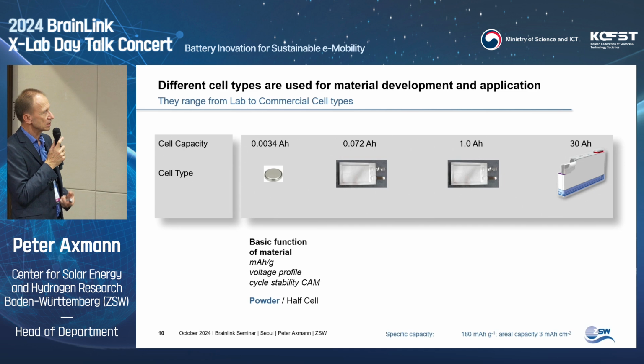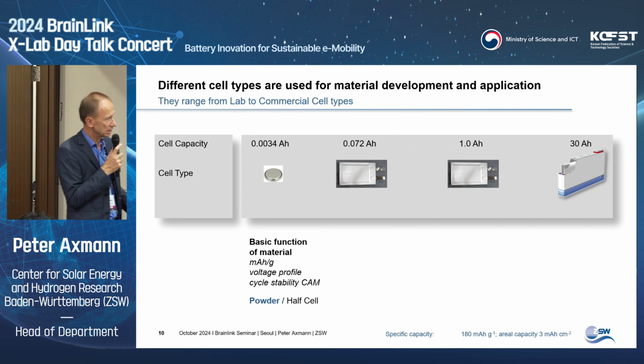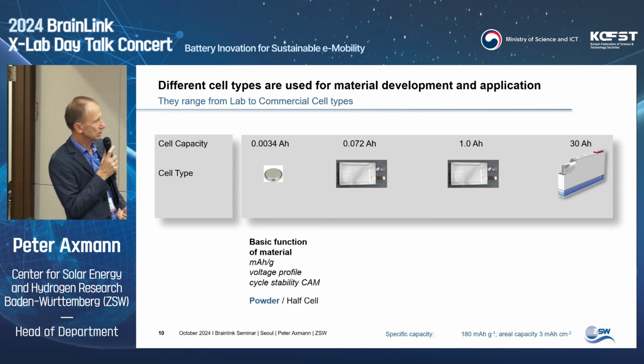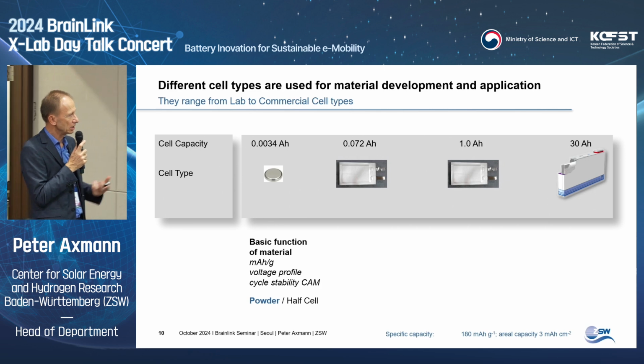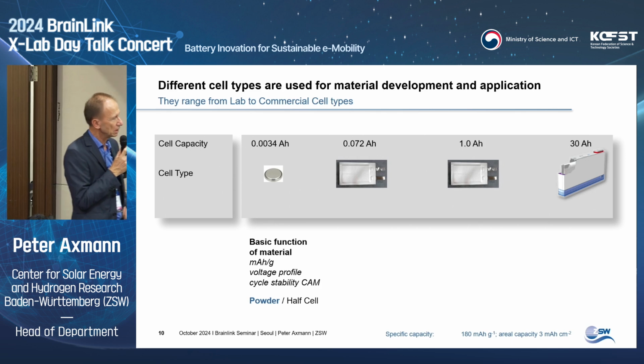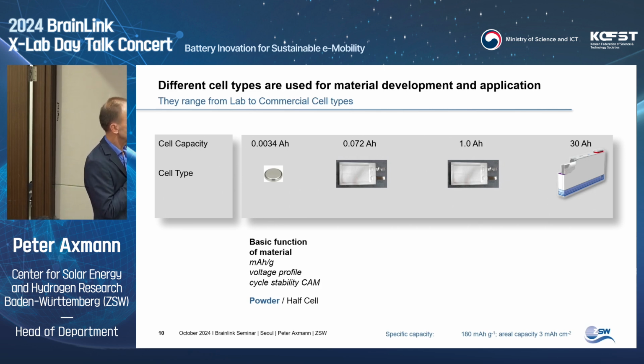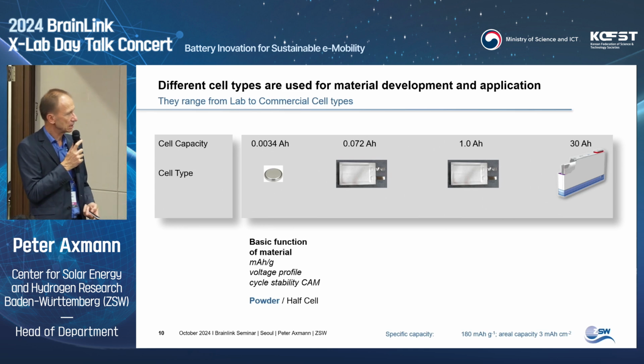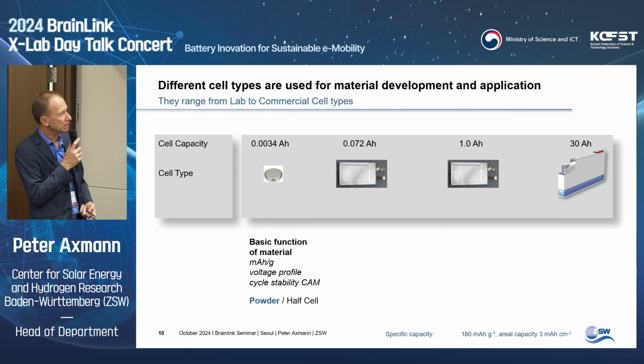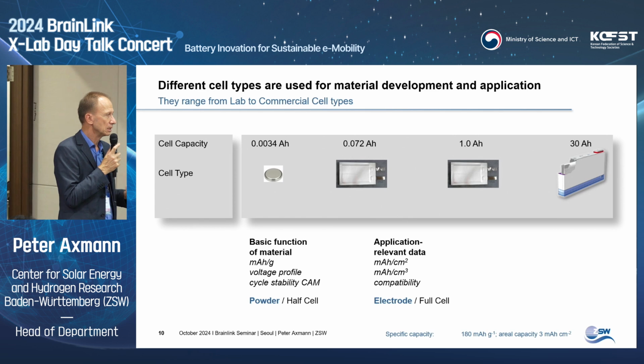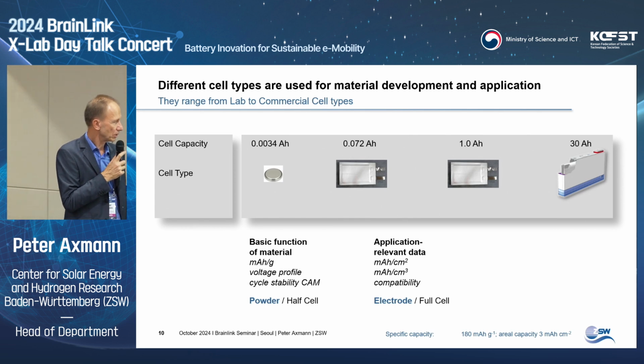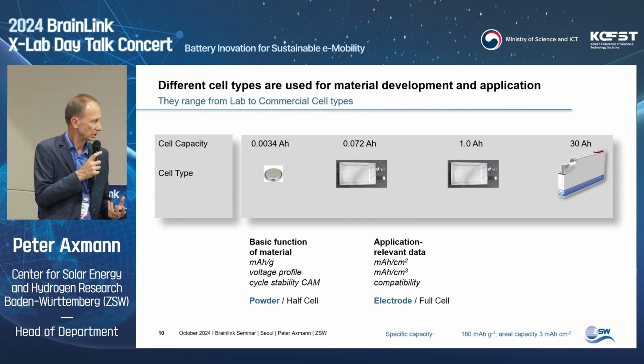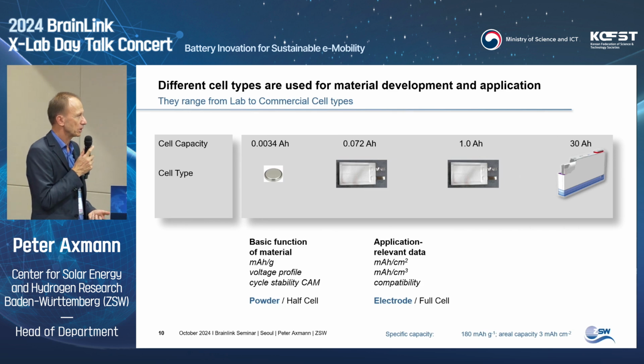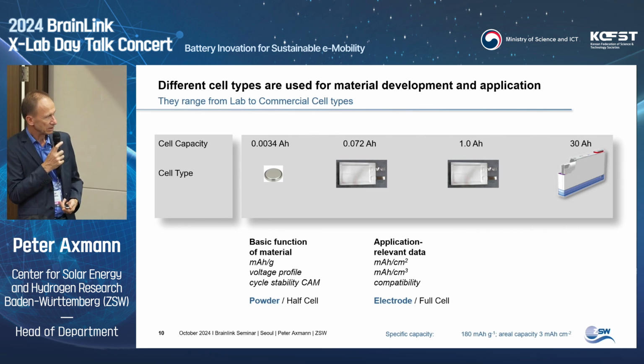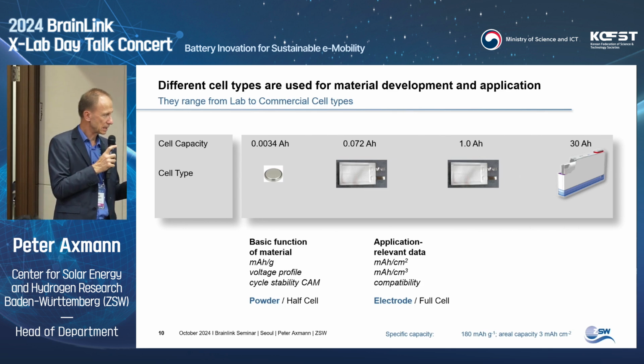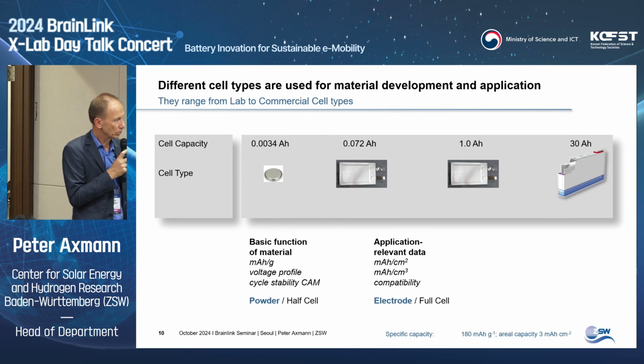And from the coin cells, the lab information you can get is just the basic function of the material. So what is the powder able to deliver in terms of charge per gram? What does the voltage profile look like? What is the cycle stability on this level? But if you go to more application-relevant data, you need the milliamp hour per area or the milliamp hour per volume you can store. You need to learn about the compatibility of the positive and negative electrode. So the focus here is more or less on the electrode and on the full cell.